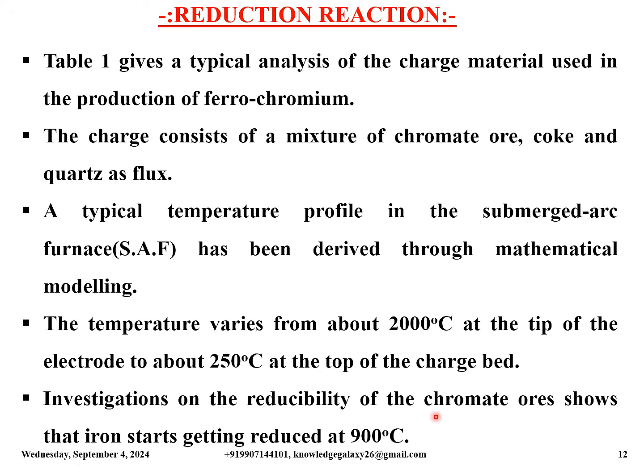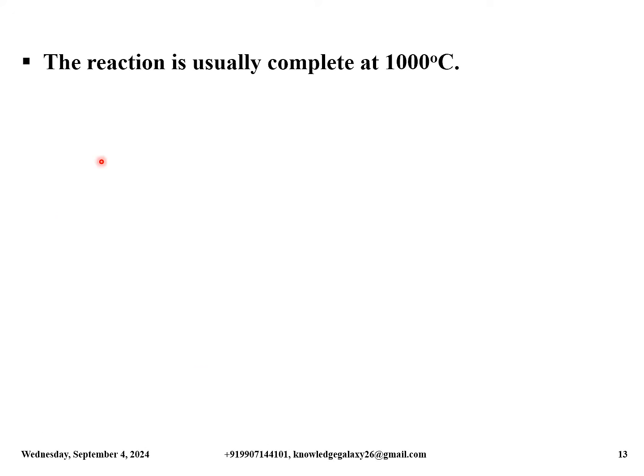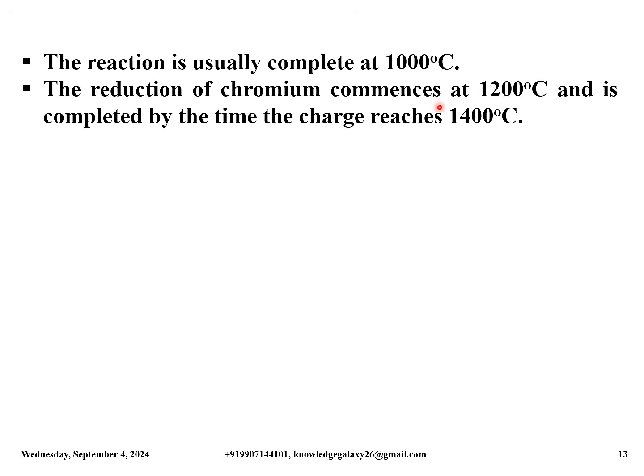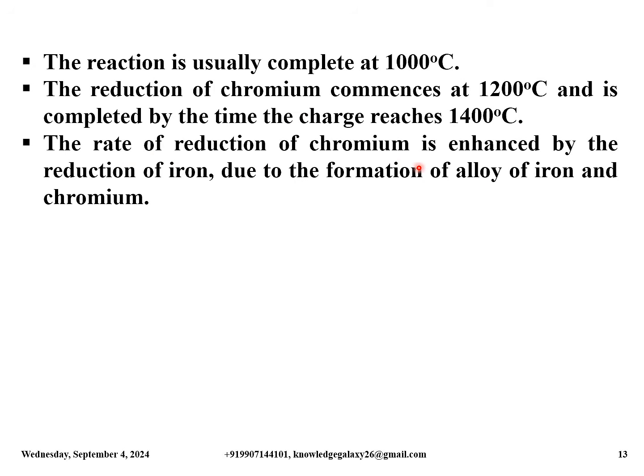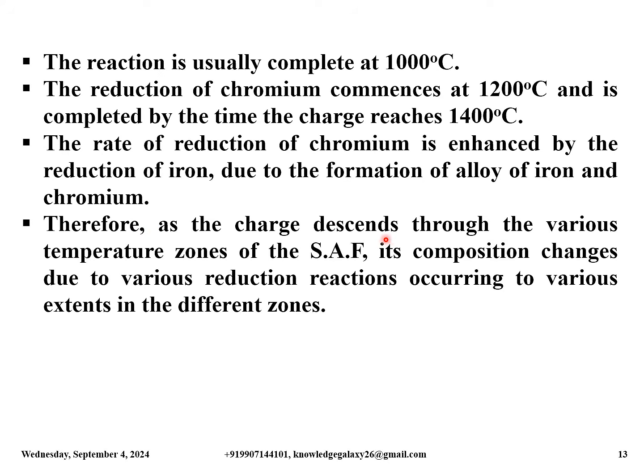Investigations on the reducibility of the chromite ore show that iron starts getting reduced at 900 degrees Celsius. The reaction is usually complete at 1000 degrees Celsius. The reduction of chromium commences at 1200 degrees Celsius and is completed by the time the charge reaches 1400 degrees Celsius. The rate of reduction of chromium is enhanced by the reduction of iron due to the formation of an alloy of iron and chromium. Therefore, as the charge descends through the various temperature zones of the SAF, its composition changes due to various reduction reactions occurring to various extents in the different zones.